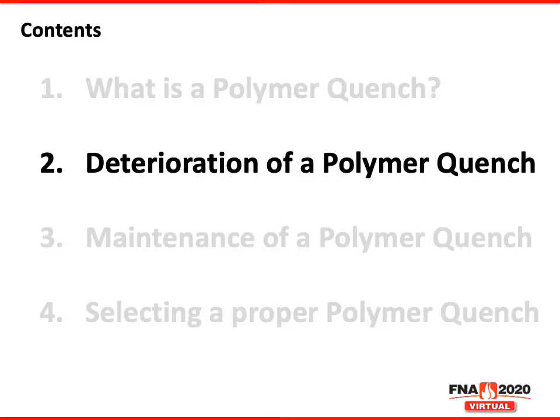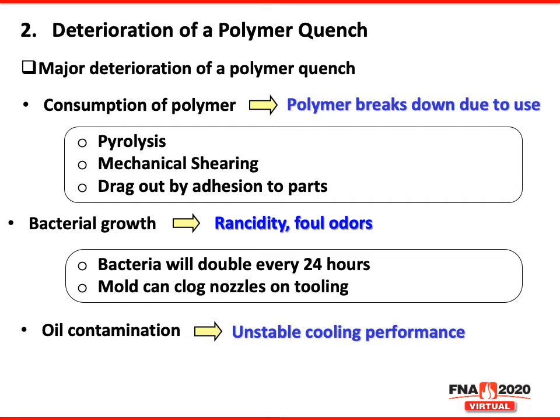So how does a polymer quench deteriorate? Well, it breaks down through use. Breaks down through pyrolysis, which is thermal degrading. Breaks down by mechanical shearing. Since it coats the parts, it's dragged out. If it's left untreated, it grows bacteria, which results in rancidity or foul odors. It's important to note that bacteria will double in size and in concentration every 24 hours.